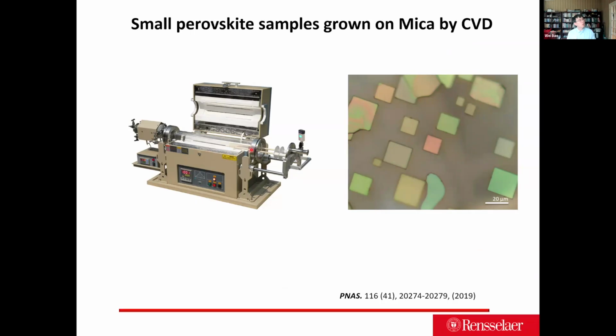However, the samples Qihua and I worked on are typically grown on mica substrate, and you CVD grow this material on top. Those typically generate a very small sample, on the order of 20 micron. Although they are single crystal, you can use the Nobel Prize method, like Scotch tape, to eventually transfer them onto the DBR at will. But the sample size is really small, and you can basically afford only a point-like measurement. Essentially, you use a laser, pump it in the center, collect the photoluminescence, and see the system run into condensate. But other than that, you cannot do much beyond it.